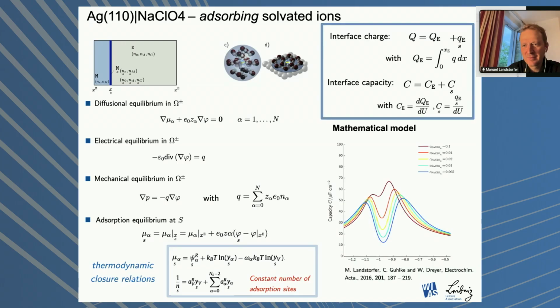And this loops back to a contribution of surface charge here, QSE. This is the amount of adsorbed charge on the surface due to these guys. And they do have also a surface capacity contribution. And this is really the origin why you can have unsymmetric capacity humps, where the right one, or this hump, actually comes from the adsorbate of perchlorate.